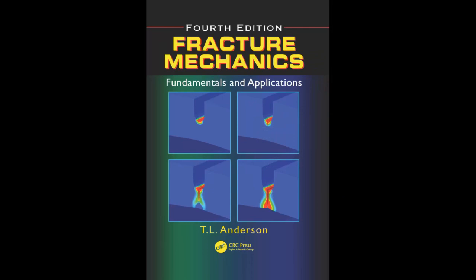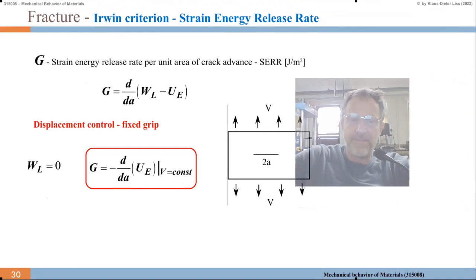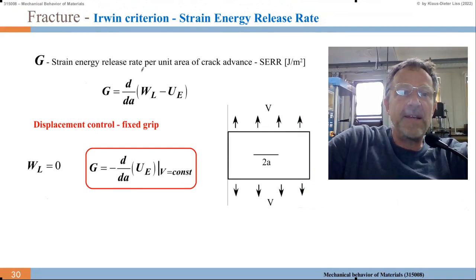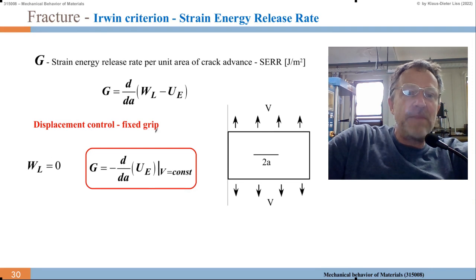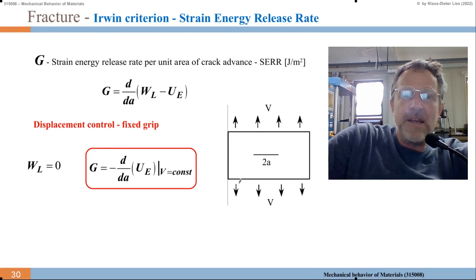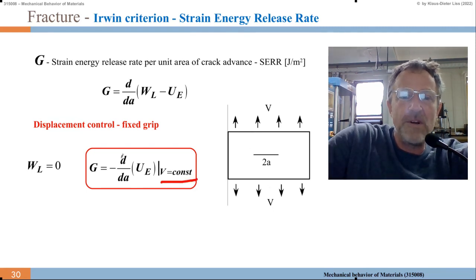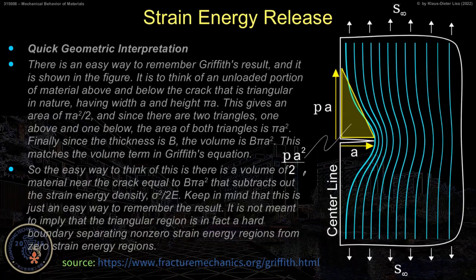This was a citation from that book. The strain energy release rate per unit area, as I wrote it down here: if we have displacement control, that means a fixed grip, we apply a displacement with constant volume — the volume is the area times the displacement. At constant volume, G becomes d over dA times U of E, so there's no external workload since the volume is kept constant, nothing happens externally.